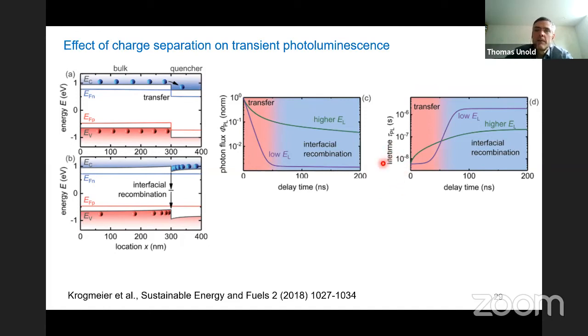A good way of showing this is if you look at this differential lifetime. So if you take at each point in time a derivative showing the instantaneous lifetime, you can see here now the interesting case, maybe if you manage to have low enough injection conditions, then first you have this charge transfer, and then you reach this case where it's limited only by interface recombination. And this is the stage where you could infer the lifetime due to interface recombination. And if you think about a steady state measurement, PL, quantum efficiency or so, that would correspond to this long time region where you have a steady state, but only if the full device is illuminated.